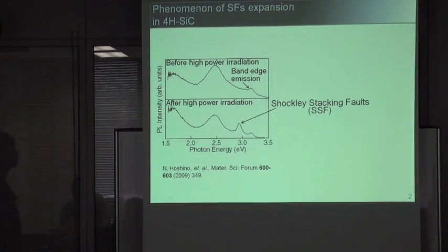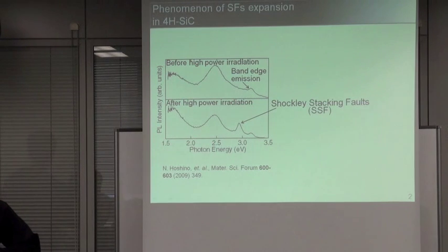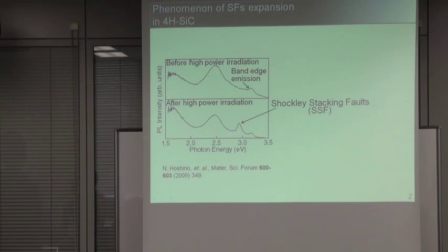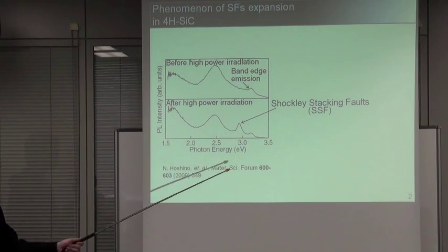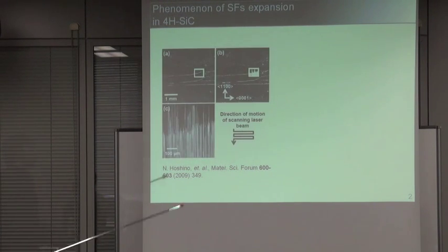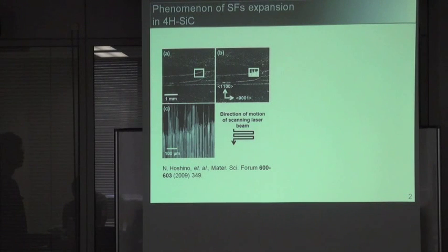As an introduction, I would like to talk about the phenomena of the stacking fault expansions induced by intensive laser illuminations. This graph shows the photoluminescence spectra before and after intensive laser illuminations. A remarkable increase of the photoluminescence peak, arising from the Shockley stacking fault, was observed after the intensive laser illuminations.